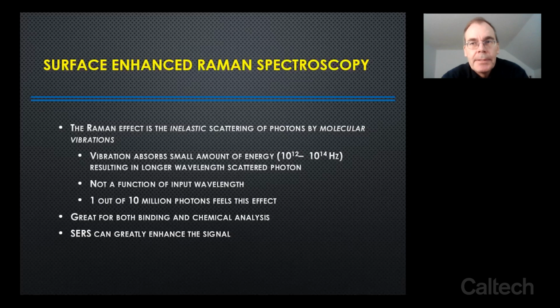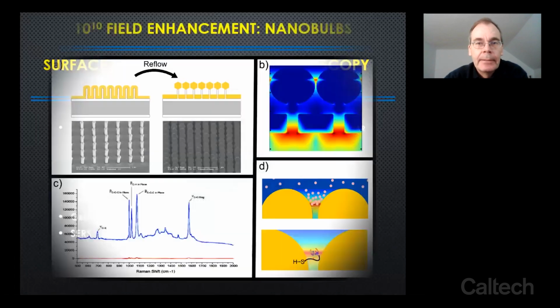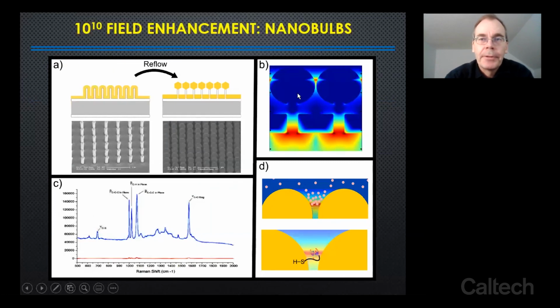The trick in order to do this efficiently is to build systems where you have a very large enhancement, a very large optical field. And we can do that by nanofabrication. So we can generate these extremely high optical fields. And in this case, we use little metal nanoparticles that we fabricate on the surface. These are little spheres of gold, and just about where they meet, so if they're 10 nanometers apart, these two spheres generate this extremely high optical field that is 10 to the 10 times higher than the surrounding light. And that allows you to do very efficient Raman conversion and generate these spectra, which can identify the molecules that happen to be in that area.